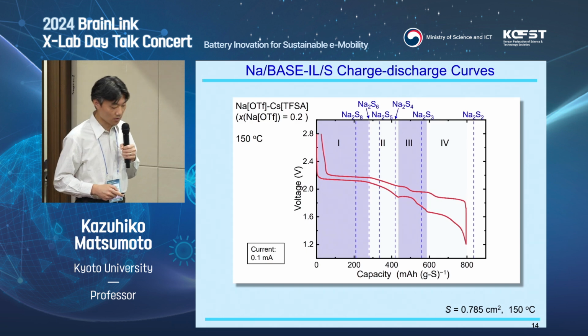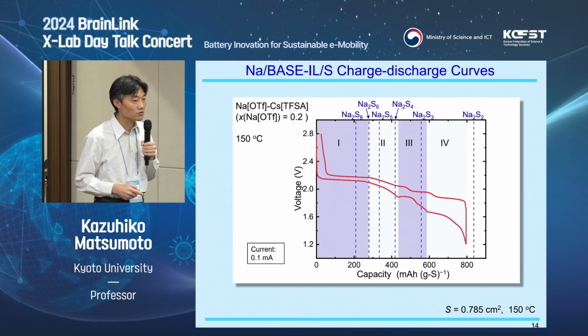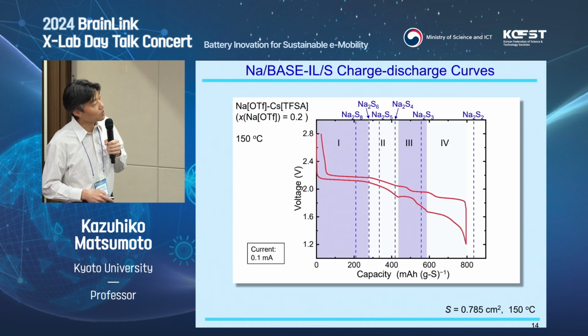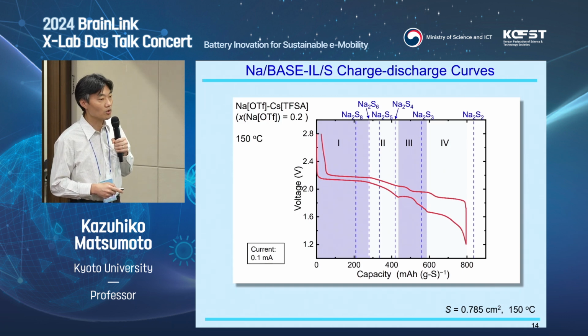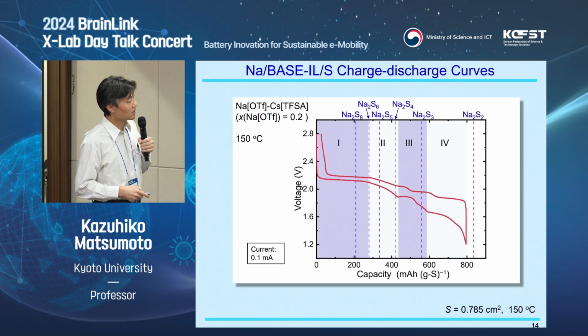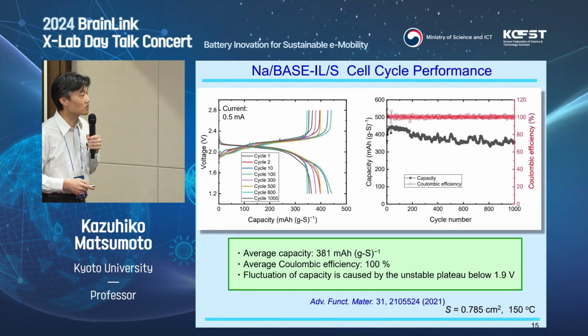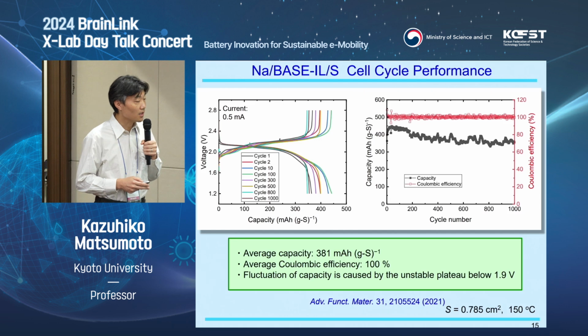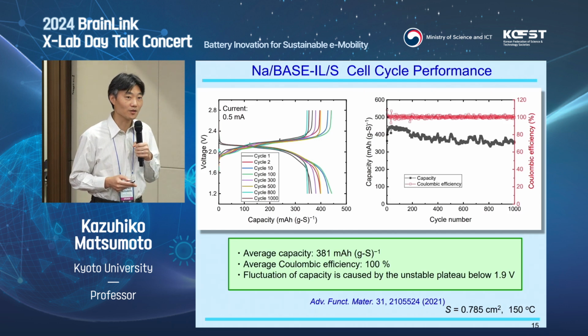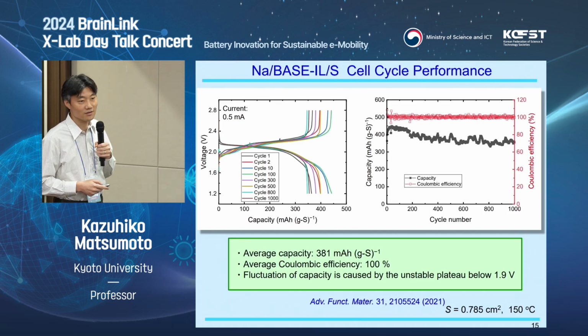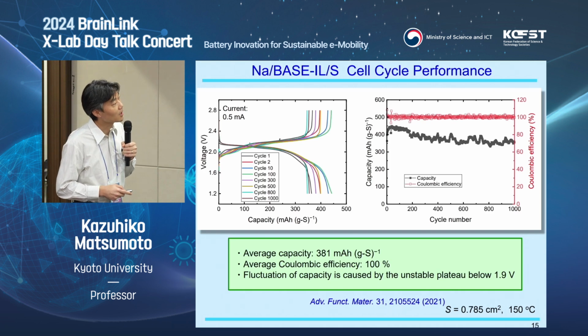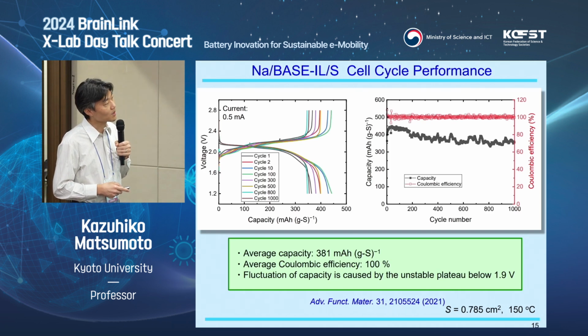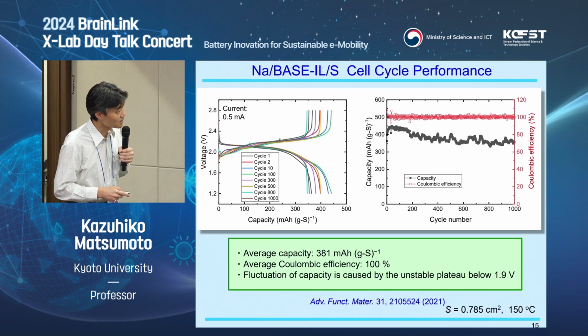And then for the first discharge, we get 800 milliampere hour per gram, nearly corresponding to the formation of Na2S2. But in this case, the current was not very high, so we increased the current and did that cycle test over 1,000 cycles. This type of sodium sulfur battery is very unstable, and even 1,000 cycles is very, very challenging. Unfortunately, the capacity is somewhat fluctuating, but that is because of the use of the capacity in this region.